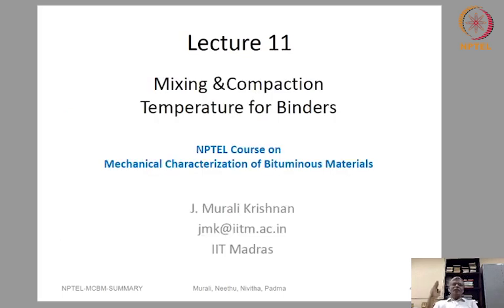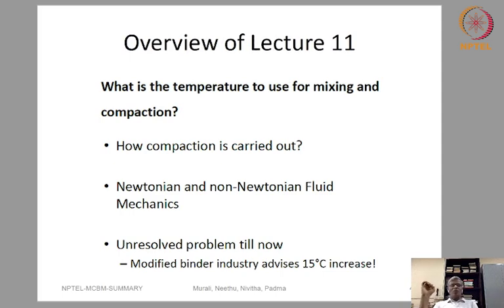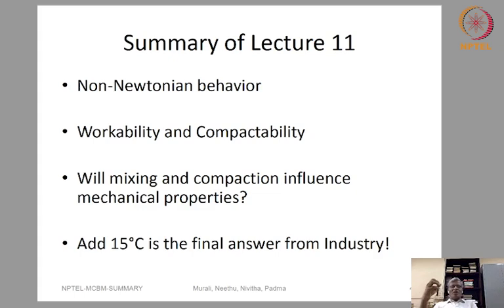In lecture 11, mixing and compaction temperature for binder, we wanted to ask only one simple question: what is the temperature to use for mixing and compaction? Here we wanted to find out how the compaction is carried out, and when it is being carried out, what is the status of the binder. There is a Newtonian, non-Newtonian transition, and as far as unmodified bitumen is concerned, there is basically no issue. But for modified bitumen, the non-Newtonian regime extends even to high temperatures. So fixing a precise temperature for starting the compaction becomes extremely difficult. Most of the time, the modified binder industry will just advise you to increase the temperature by 15 degrees centigrade.